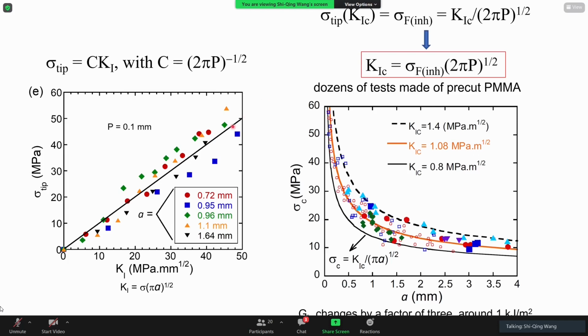Moreover, as I said, this relationship holds all the way to the point of fracture, at which I'm indicating that my tip stress is at Kc. So we end up having a relationship showing that the tip stress, which reaches inherent strength, is correlated with Kc through a characteristic length scale that indicates the stress saturation zone.